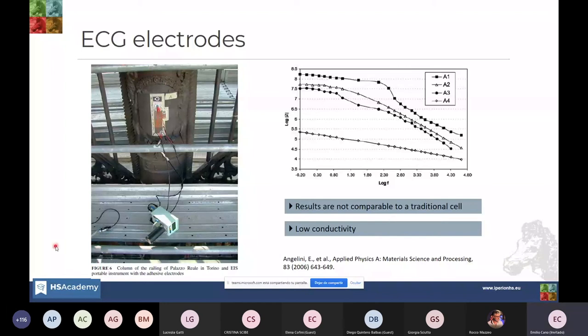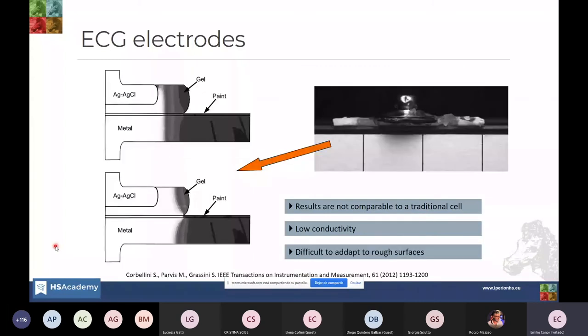these electrodes, and this is something that has already been recognized and studied by this group, and they demonstrated using this kind of simulation that depending on the conductivity of the surface of the metal and the paint or the coating or the patina applied to that, the area you are studying is different. And this can also change with the frequency you are applying. So that could explain these strange results. They also highlighted the difficulty to adapt to rough surfaces because it cannot adapt and fill all these gaps in a rough surface. So you don't really know which is the real surface you are analyzing.